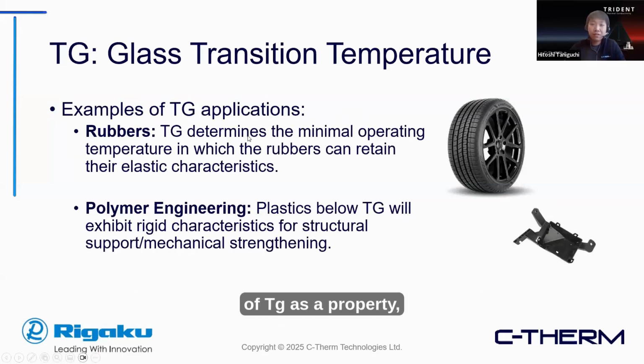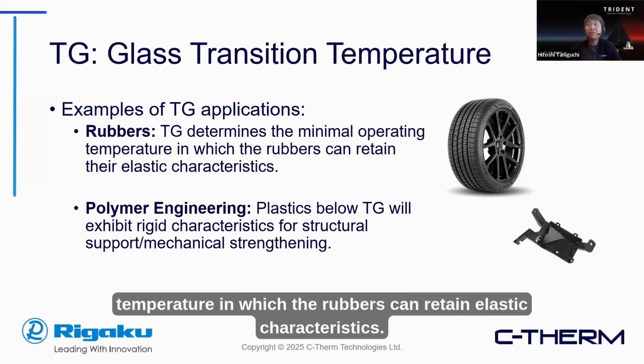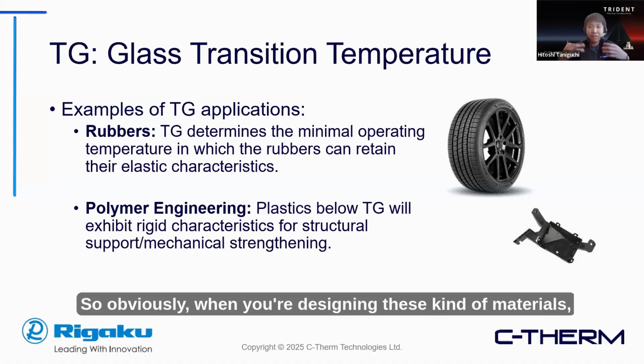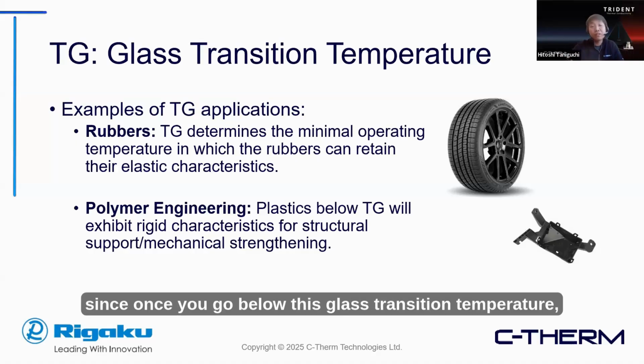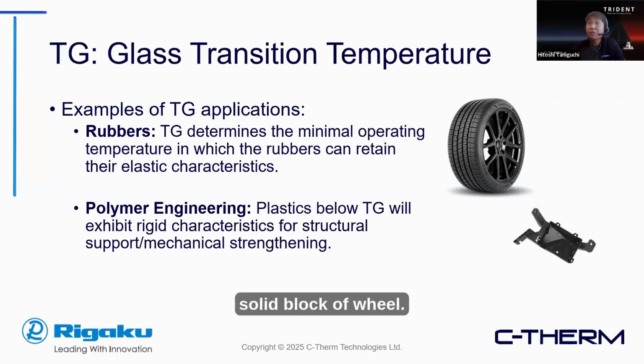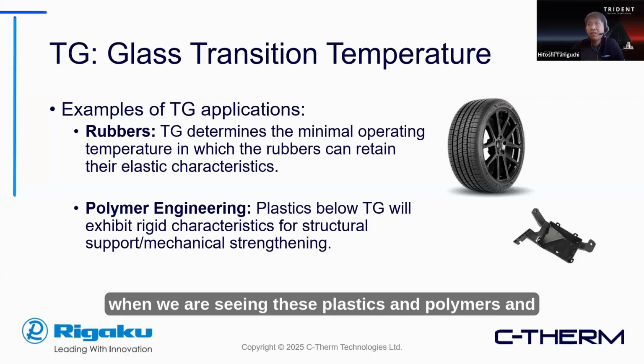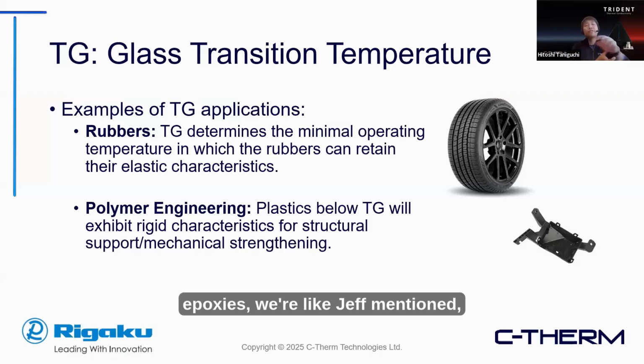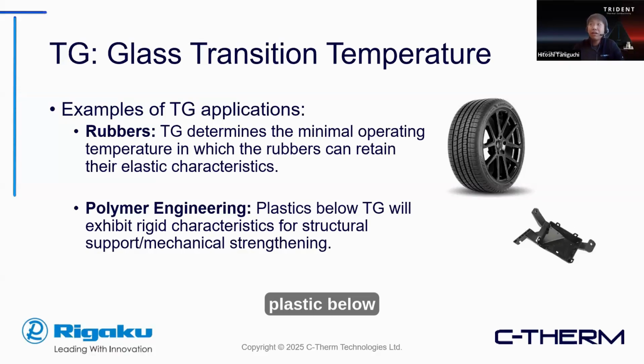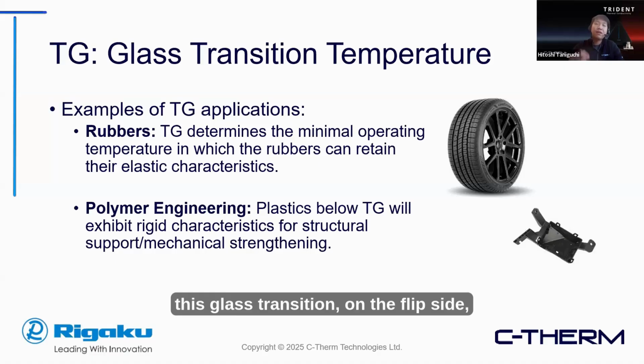One of the common applications of Tg as a property is the rubber industry, since Tg determines the minimal operating temperature in which rubbers can retain elastic characteristics. Obviously, when you're designing these kinds of materials, you want to keep this in mind, since once you go below this glass transition temperature, your rubber will no longer have this dampening effect, and it would just be a rigid, solid block of wheel. And especially in polymer engineering, when we are seeing these plastics, polymers and epoxies, like Jeff mentioned, being packaged into different systems, whether it be electronics or even automotives in some cases, plastic below this glass transition, on the flip side, will retain these rigid characteristics, and is great for structural support and providing mechanical strengthening. One of the most common methods to measure this property is differential scanning calorimetry, or DSC.